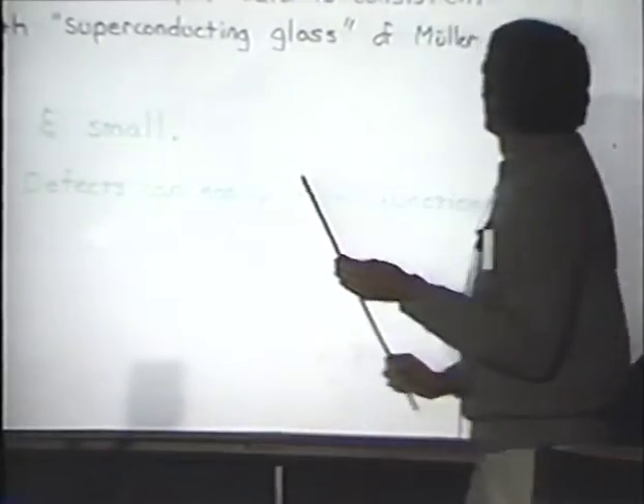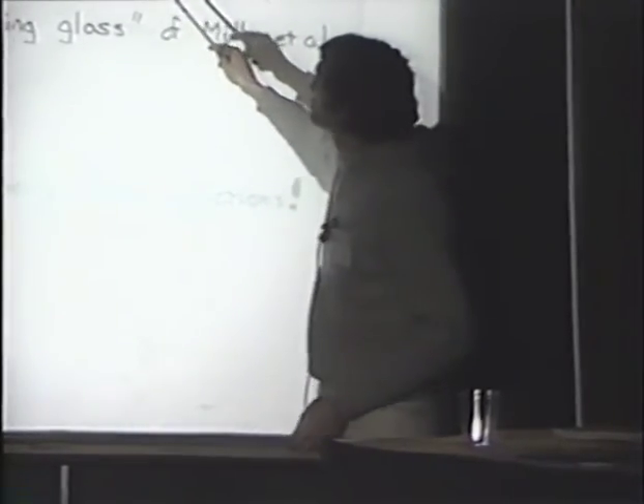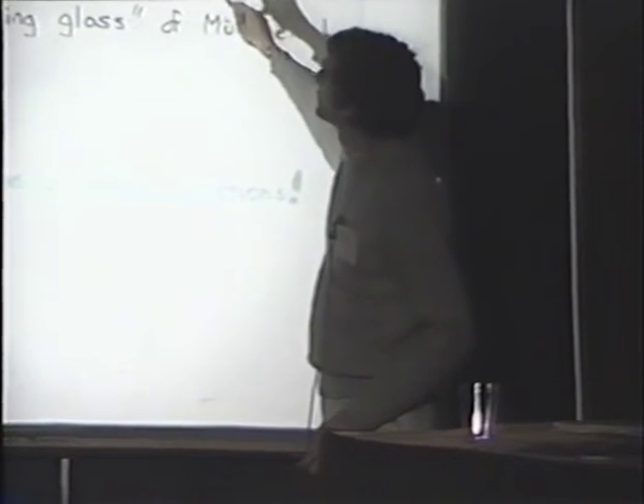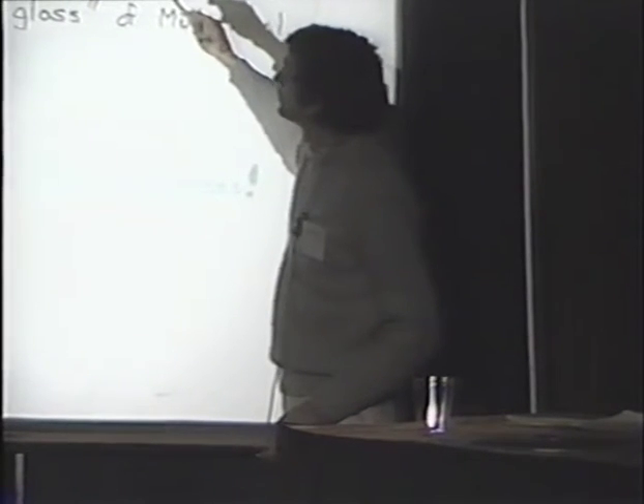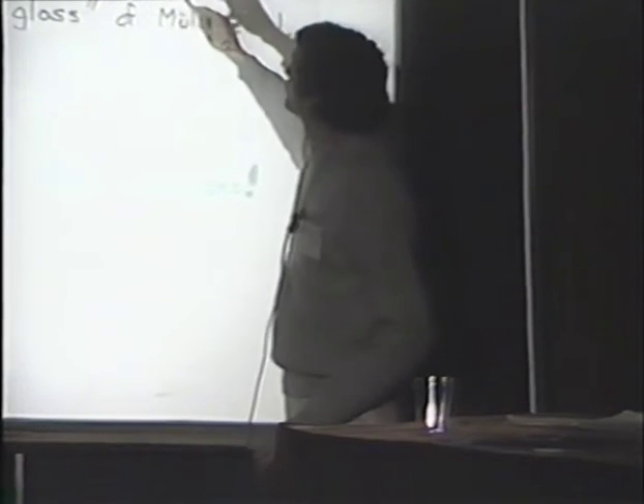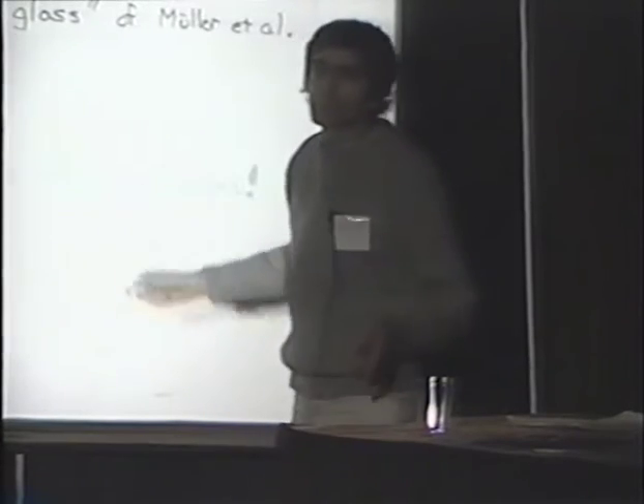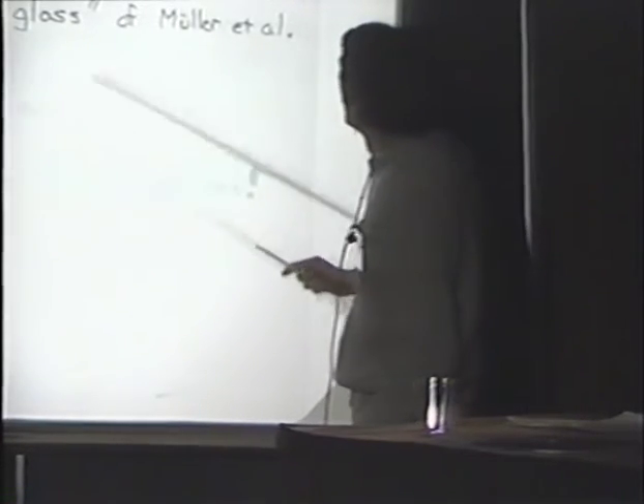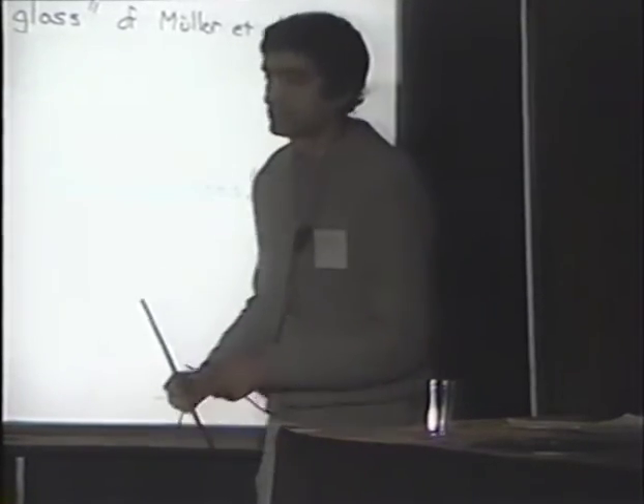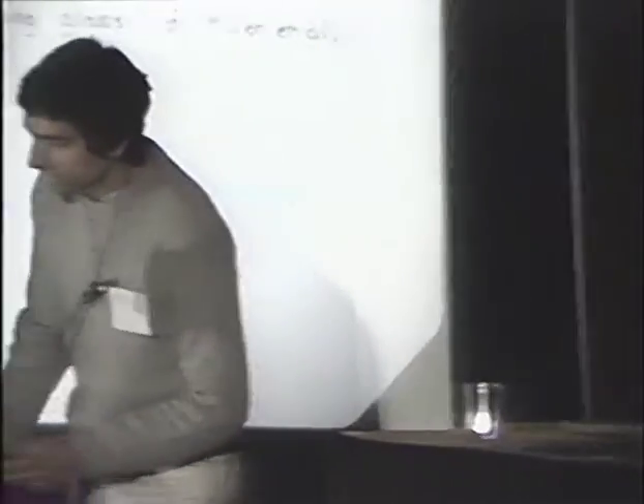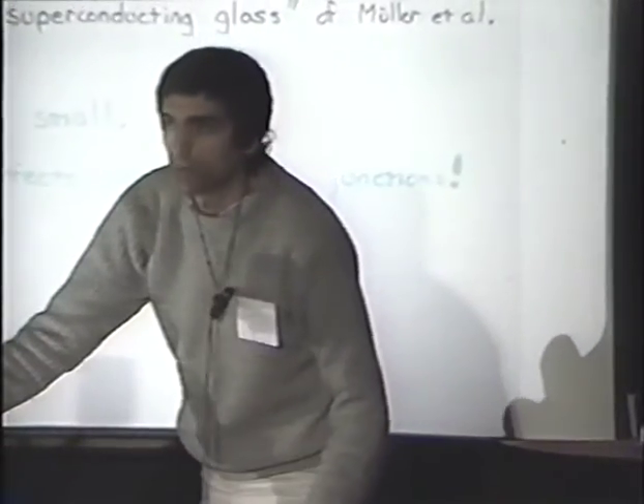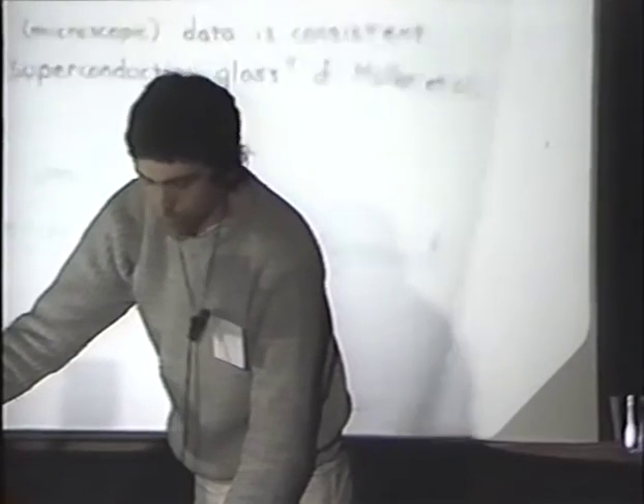A very simple microscopic model is that we have superconducting islands that are connected via junctions. Our tip makes contact with one of these islands, and then the current flows into the sample. If magnetic field threads through one of these SQUID loops, we get the modulation with magnetic field. I note this model is consistent with the superconducting glass model of this material proposed by Müller et al.